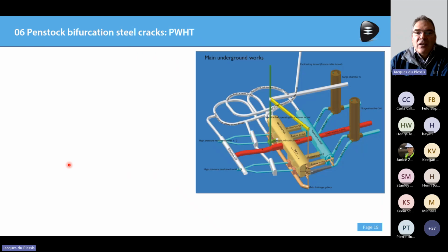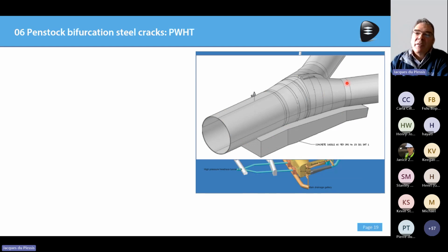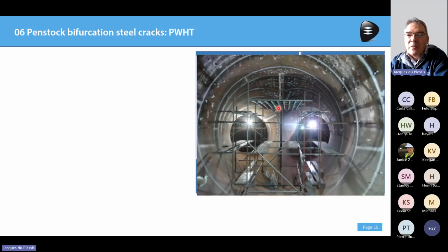Okay, looking at the inclined high pressure shafts coming down at that bifurcator upstream of the turbines. We had this steel bifurcator plate and a crotch plate in the middle. So you've got the shell welded to that crotch plate. To show you a photograph, there's that 150 millimeter plate in the middle. And then the shell, 46 millimeter thick steel of that rock tough steel, welded to the plate in the middle.